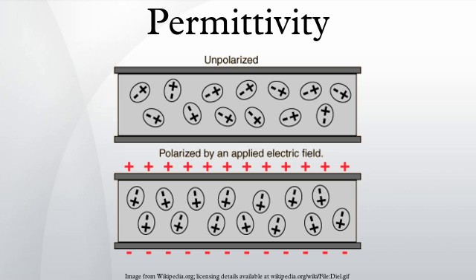Since the response of materials to alternating fields is characterized by a complex permittivity, it is natural to separate its real and imaginary parts, which is done by convention in the following way: epsilon' is the real part of the permittivity, which is related to the stored energy within the medium; epsilon'' is the imaginary part of the permittivity, which is related to the dissipation of energy within the medium; delta is the loss angle. It is important to realize that the choice of sign for time dependence, exp(i omega t), dictates the sign convention for the imaginary part of permittivity. The signs used here correspond to those commonly used in physics, whereas for the engineering convention one should reverse all imaginary quantities.